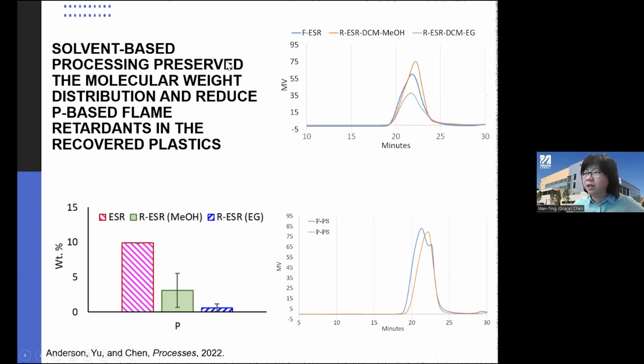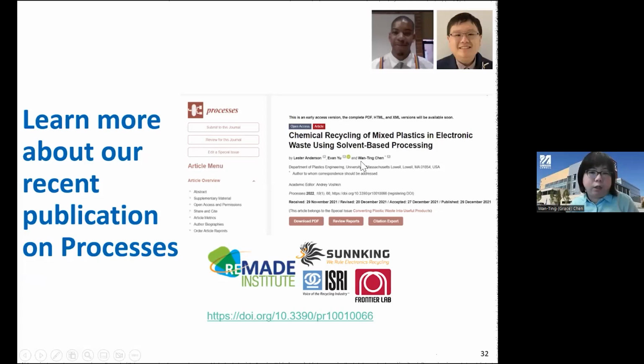And we also want to purify it, remove those unwanted things. So what we show here is that by using this dissolution-precipitation technology, we were able to preserve their molecular distribution, which is a good thing actually. And we found that the feedstock-based polystyrene and the precipitated polystyrene share very similar molecular structure. A similar trend was also found here. Again, I would encourage you to take a look at this journal article if interested.